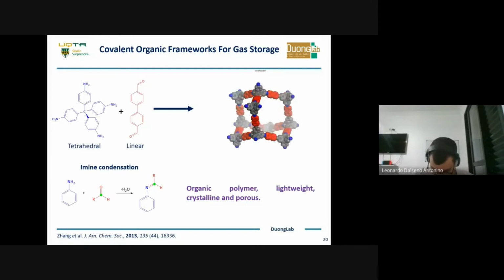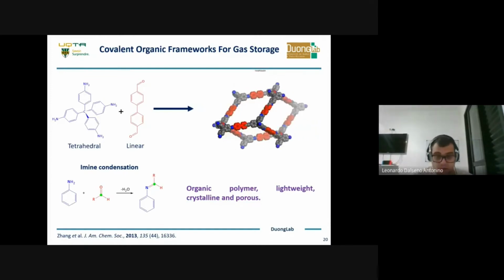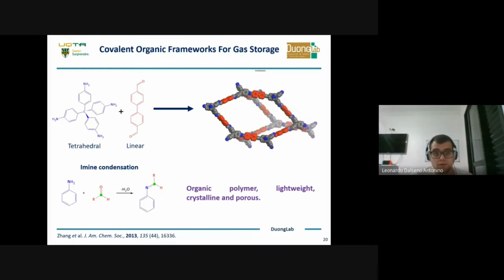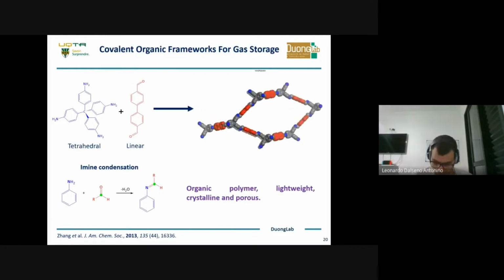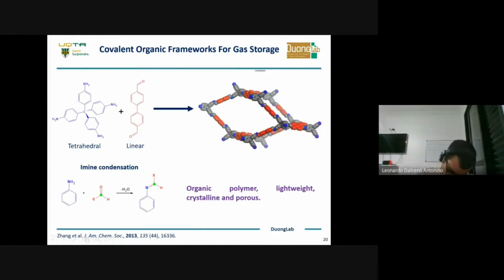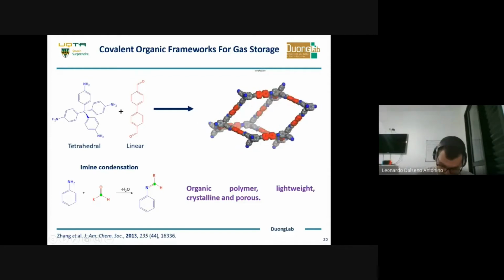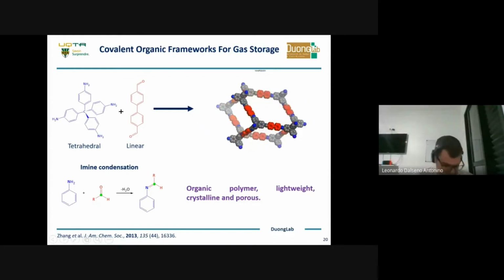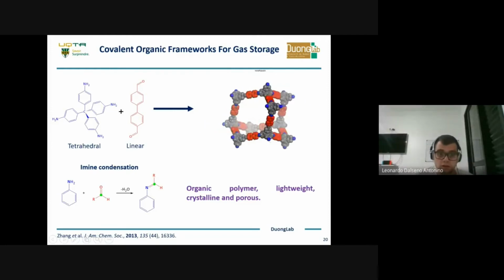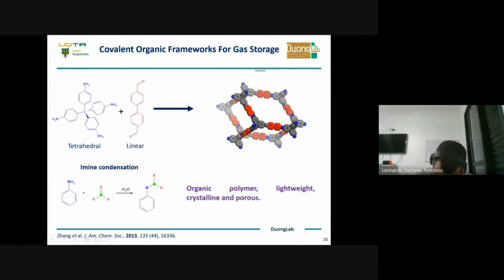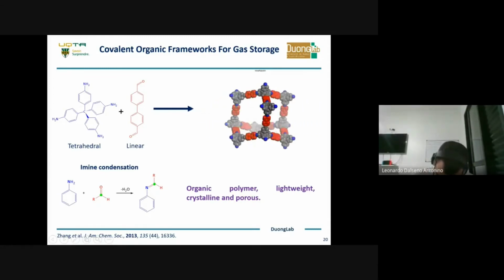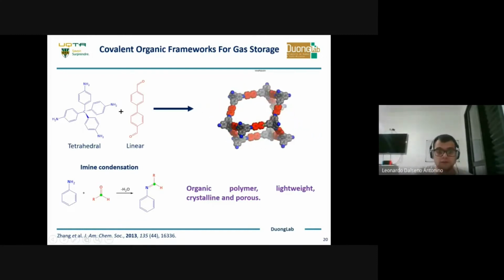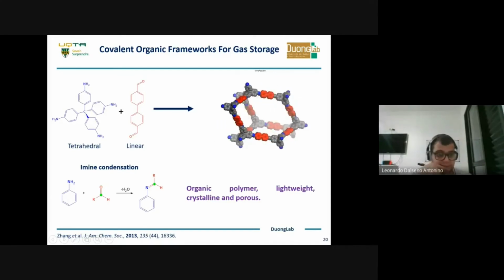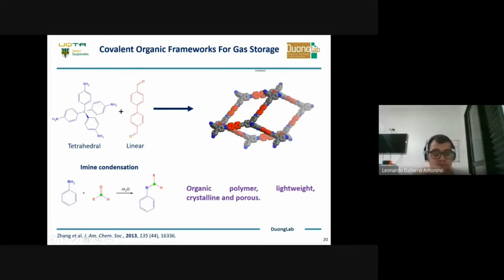The second example that I would like to show you is the synthesis of a covalent organic framework for gas storage. You can use this tetrahedral compound with four amino groups at the extremities of a tetrahedral core, and this building block with aldehyde groups. If you know a little bit about organic chemistry, when you mix an amine with an aldehyde and heat both compounds together, you release water, but you form what we call the imine bond.